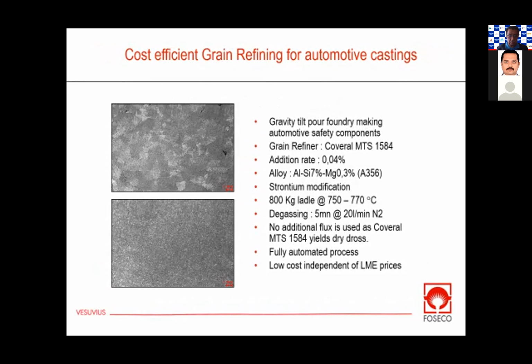All of you know that in sand, in gravity, and in low pressure, titanium boron grain refining is a very important part of the process. And especially when you do safety components, you know that the mechanical properties, whether it's elongation or UTS, are directly correlated to the grain size. Of course, there are other things—oxides and other parameters that affect these mechanical properties—but grain size is a critical factor.